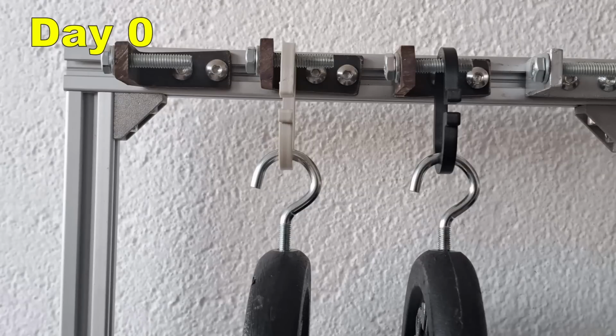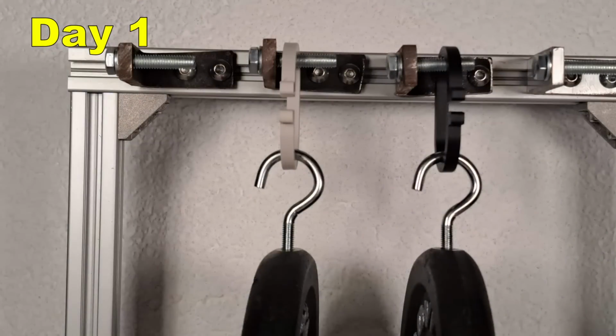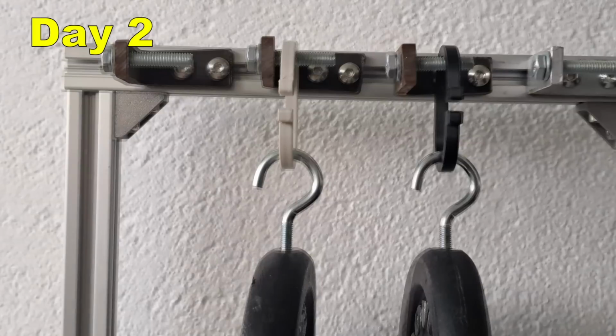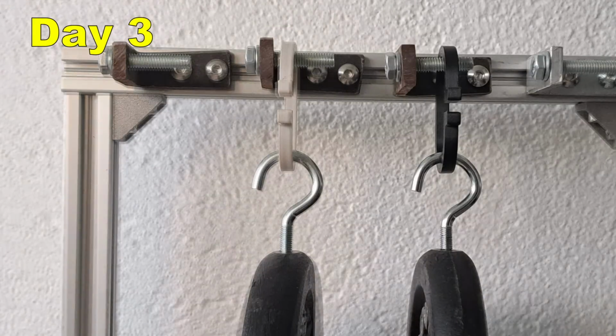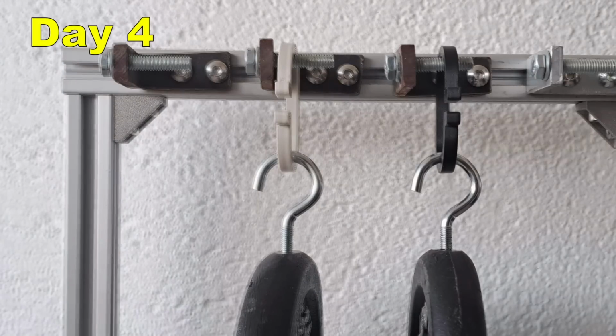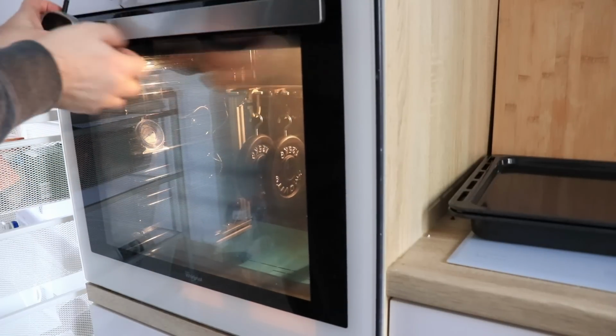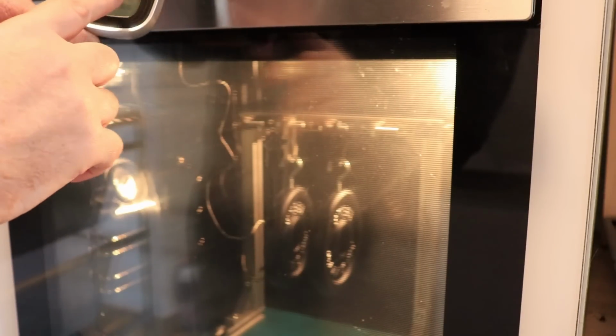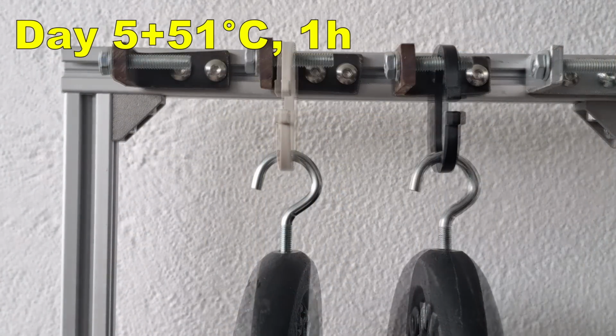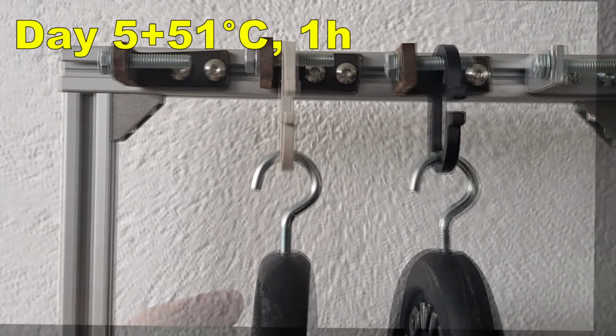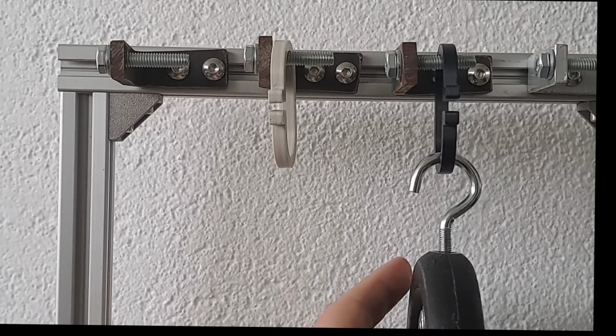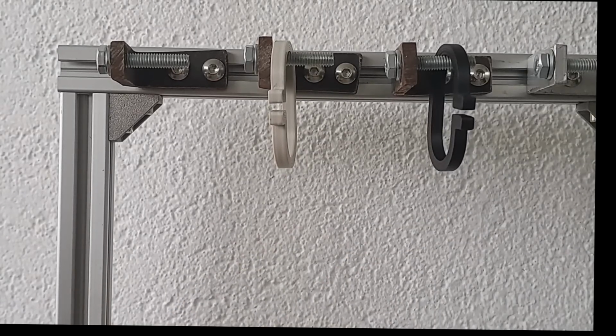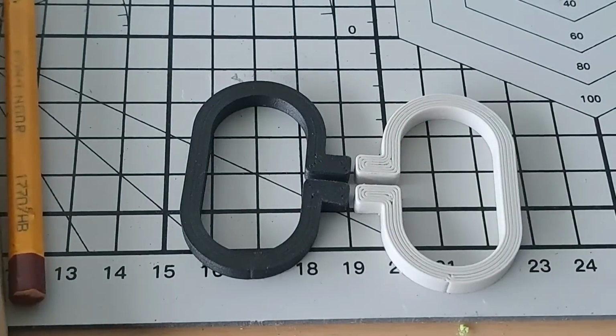This is day 0 with initial deformation, day 1 after 24 hours, day 2, day 3, day 4, and after day 5 I place them in the preheated oven. Temperature was approximately 51-52 degrees Celsius, and now let's measure them. So this was day 5 before heating, and this after 1 hour at 51 degrees Celsius. And I always like to record the removing of the load. And 10 minutes later this is the deformation after removing of the load.